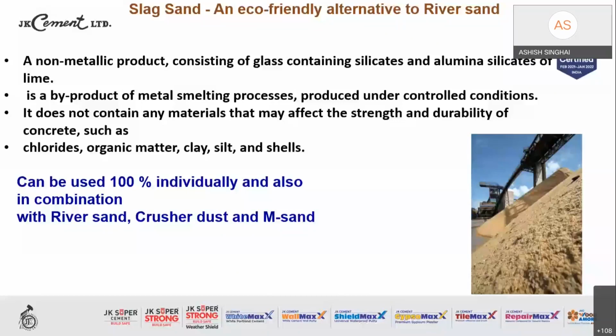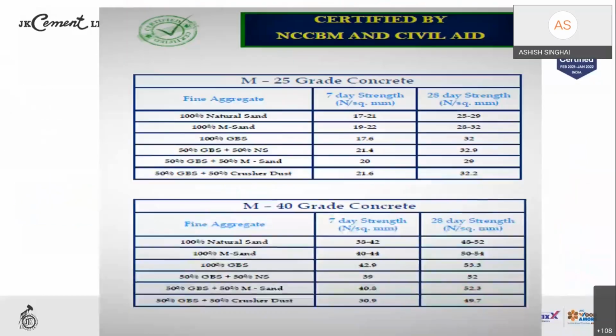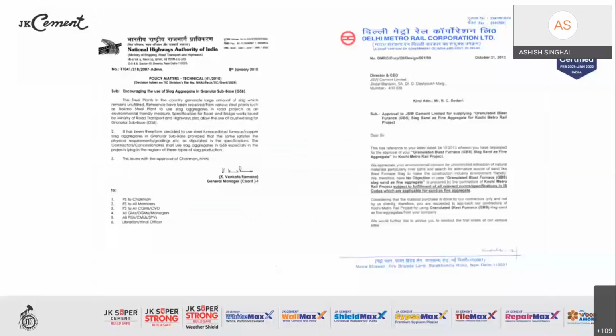A lot of studies have already been carried out, and NCCBM has mandated its use. And as you can see, different percentage levels of natural sand, M sand, this GGBS blast furnace slag, and then below, combinations of this GGBS blast furnace slag with natural sand, with M sand and crusher dust. You find that the 7-day and 28-day strengths are better when the slag sand had 50% replacement. So that gives a very good idea, and we have got figures in place to go ahead with. NHAI and Delhi Metro Rail Corporation have all done their own studies and given certificates that it can very well be used as a replacement or partial replacement to the river sand.